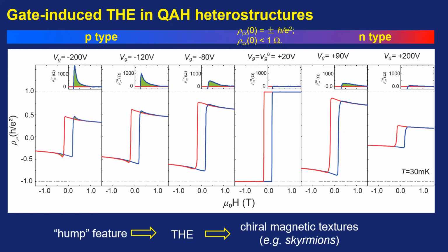But I just tried 20 samples with the calibration of the previous postdoc, and we finally got one very good quantum anomalous state. So the vanadium-doped system is much easier than the chromium-doped system. So some DFT calculation sometimes is not very accurate. Yes, because there could be multiple effects. There could be just thermodynamically that won't make sense, or it could be the fact that the oxidation state is wrong. Yes.